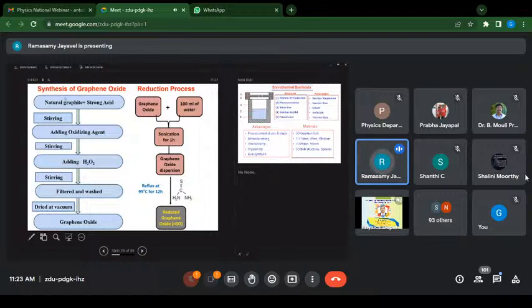And we take natural graphite as the source material because natural graphite is available in abundance, and you can mix it with very strong acids like HCl, H2SO4, HNO3, any kind of strong acid will do, only to isolate the layered structure. And then once the isolation is done, we can deliberately introduce the oxygen functional group through an oxidizing agent. And then you can just sonicate and filter it and wash it out to make the graphene oxide powder. And this graphene oxide powder can be mixed with water, and sonication for 1 hour leads to graphene oxide dispersion, a colloidal solution.